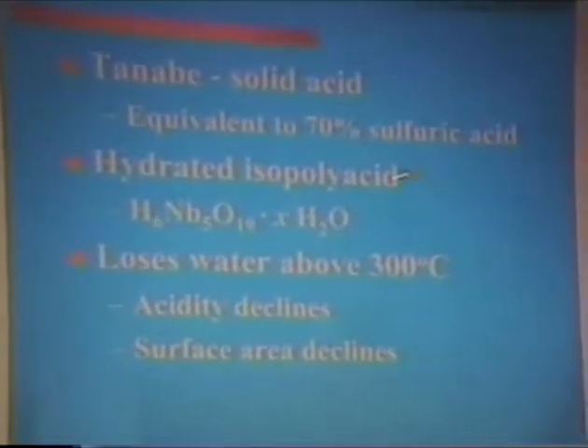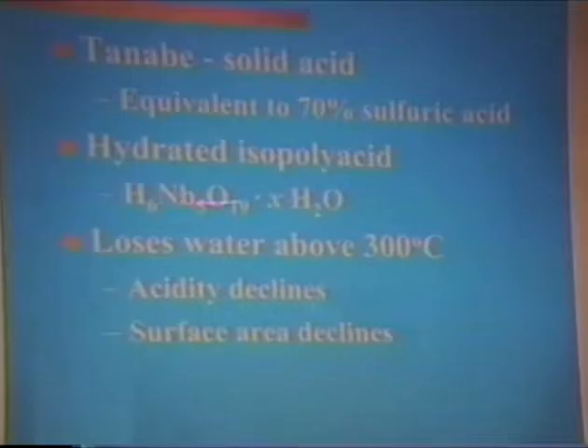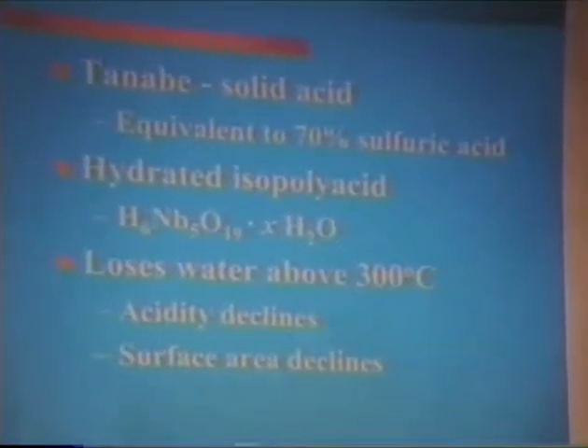This hydrate is a solid acid. It has equivalency to roughly 70% sulfuric acid. It's an isopolyacid, falling into the class of the polyoxymetallates. Generally, this composition with some variation. One of the difficulties is that it loses water above 300 C. As you raise the temperature, the acidity declines, and the surface area declines. If you're operating, however, in an environment in which water is either part of the feedstock or one of the products, you can actually do very nicely.